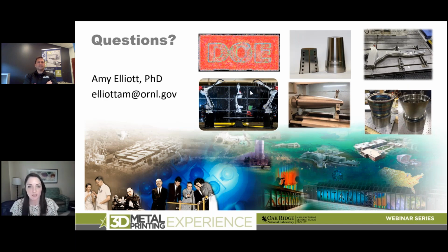So we actually had kind of a big media buzz around that earlier this year. We were able to print sand as strong as concrete. And that's great for tooling. You wouldn't use this for sand casting, but you can actually use it for like a carbon fiber layup. You put a coating over the sand tool, and then you can put your carbon fiber layup over it. You can put it in an autoclave, works great. And so yeah, a lot of our patents are around the actual materials that go into the printer. Hopefully we'll be designing new printers themselves and getting IP around the actual mechanisms, but so far it's mostly been materials.